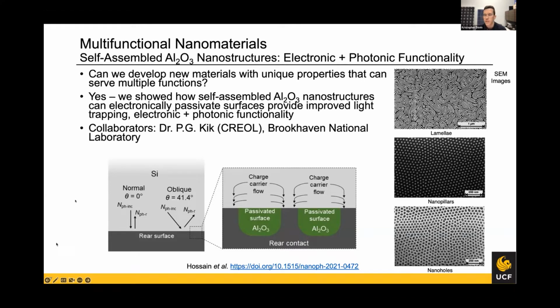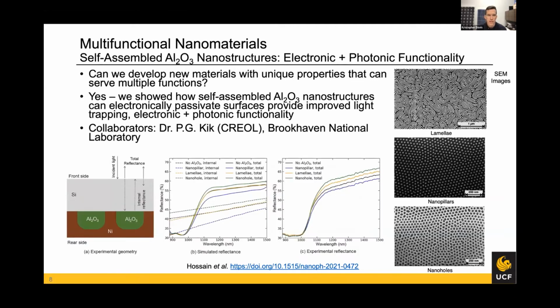We can basically use them to improve light trapping and also help passivate these surfaces, so they can lower optical losses and lower recombination losses at the same time. And we were able to confirm this experimentally, doing simulations and some experiments to confirm that indeed these can perform well. And now we're actually looking for funding on how to integrate this into solar cells as well as other potential devices.